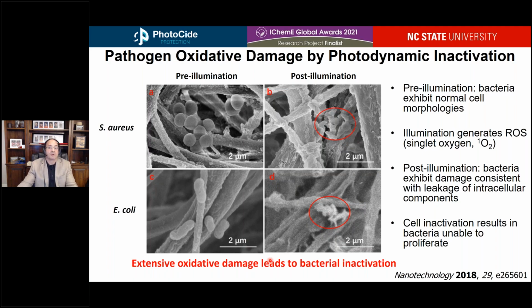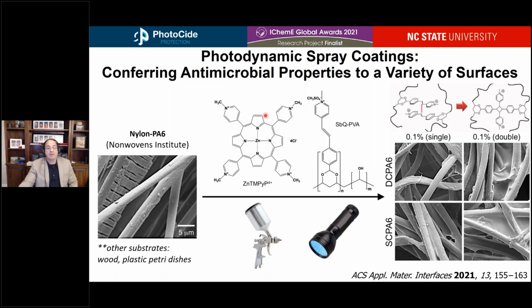So what's an example of one of our coatings that we've developed? Here we have a very simple bicomponent mixture of a photodynamic agent that we can synthesize in the lab, but it's also commercially available, that we can combine with a photocross-linkable polymer, SBQ-PVA, as a bicomponent spray formulation. This bicomponent spray formulation, as an example, we can spray it onto nylon PA6 nanofibers that were provided from the NC State Nonwovens Institute. These nanofibers, instead of polypropylene, could be used as a nylon-based version of N95 mask material. But we've also sprayed this bicomponent mixture on other substrates such as wood, petri dishes, plastics, and glass.